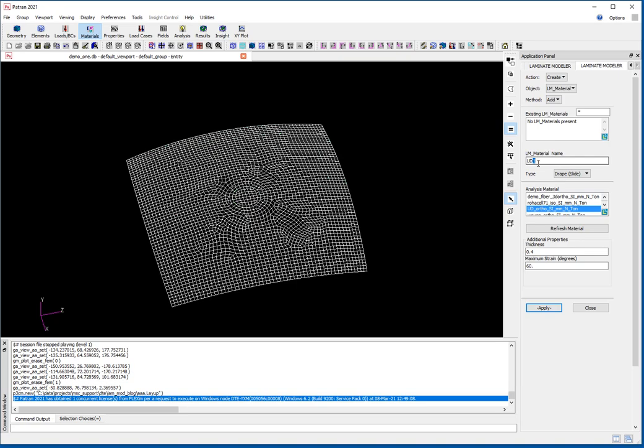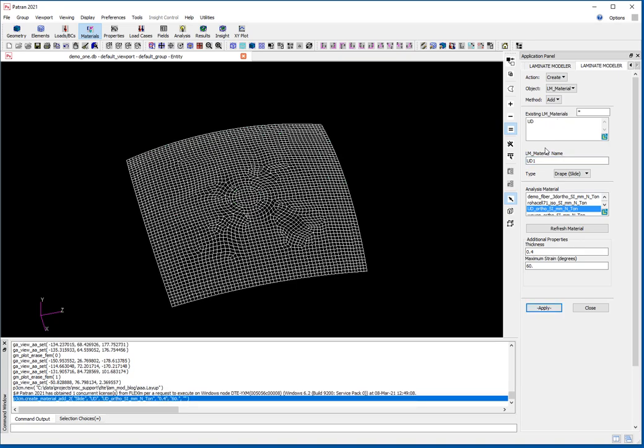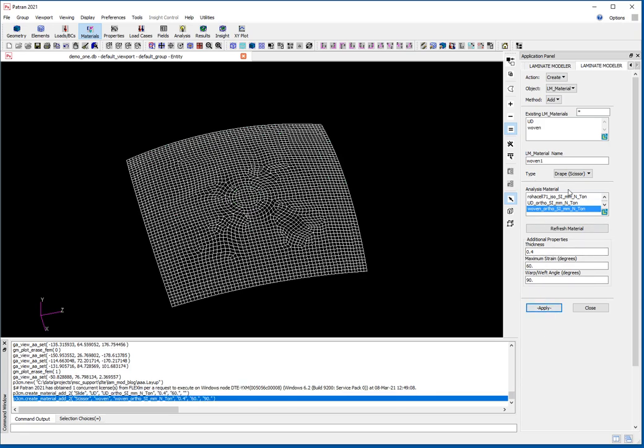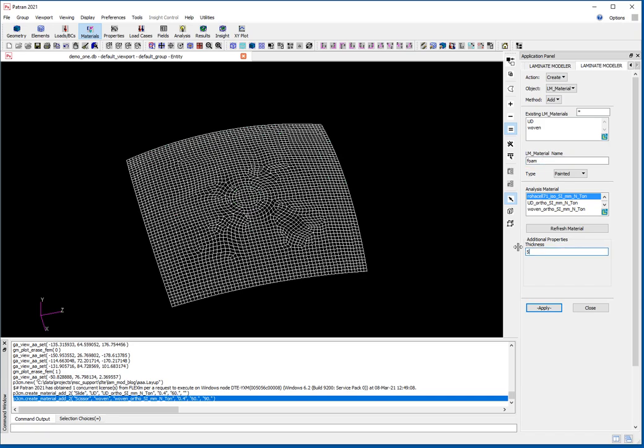I'll change the name to UD. I'm then going to have the woven material, which uses a scissor type draping, and set that to 0.4 mm thickness as well. And then lastly, using the painted type, I'm going to define the foam. That has no draping at all — it just assumes a uniform thickness — and I'm going to set that to 4 millimetres thick.